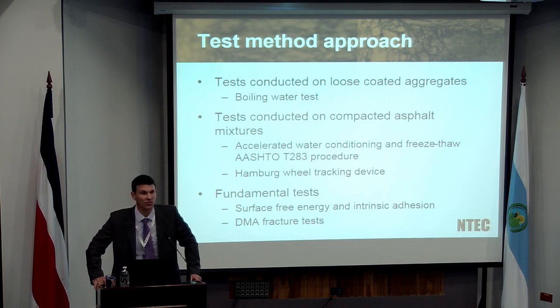And there are even tests to do it on a fundamental level. So I'm going to talk a little bit about that in a second. So using surface energy to measure intrinsic adhesion, in other words, using a theoretical calculation to understand the adhesion between our stone and the bitumen. And then even looking at direct measurements of adhesion. So for example, we saw walking around your lab some examples of the PATTI test, which is a standard pull-off test used to determine some form of adhesive or cohesive failure of an aggregate bitumen system. So there were tests available.